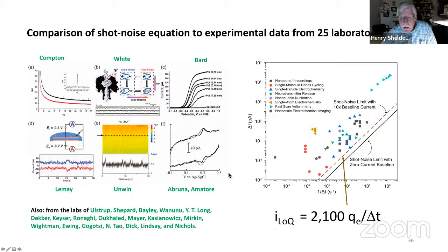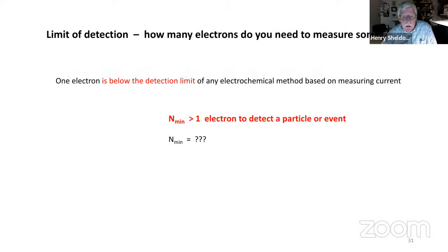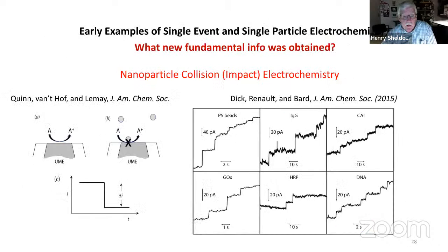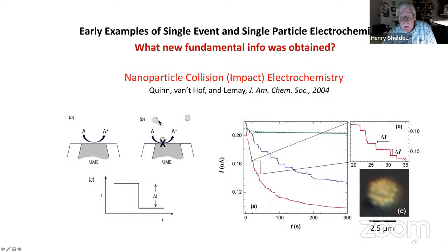All right, and then on particle collision experiments, there's a lot of them. I didn't talk about them because I just don't have time. Instead of doing this experiment where you're looking at insulating particles, this could be a catalytic particle that comes down to the surface. When it hits the surface, there's a burst of current or step increase in the current from the catalytic reaction that's being carried out. So you can start looking at rates of reactions as a function of the size and the shape of the particle. Effects of the shape of the particle.